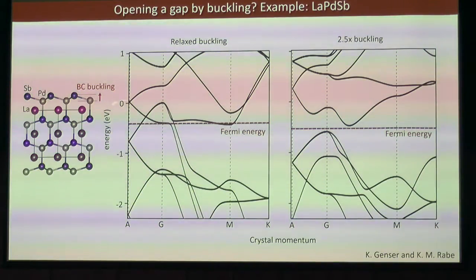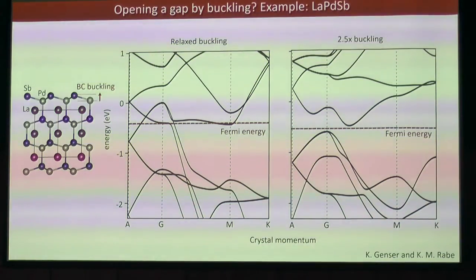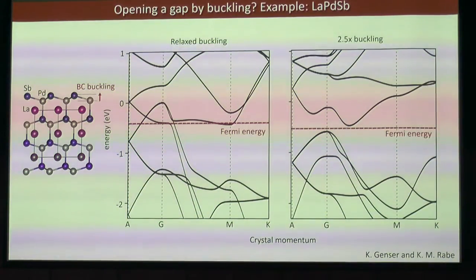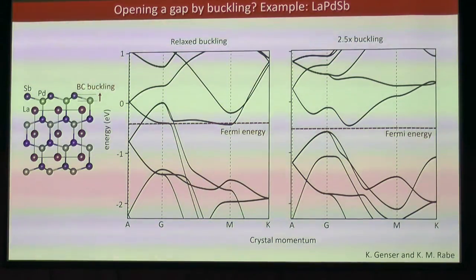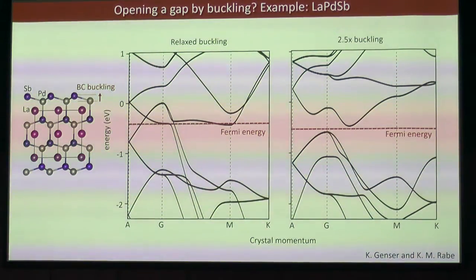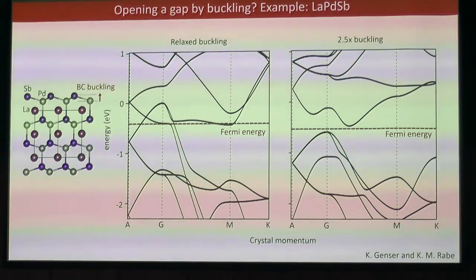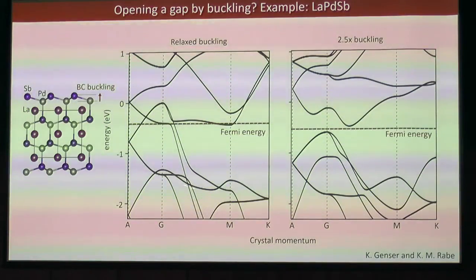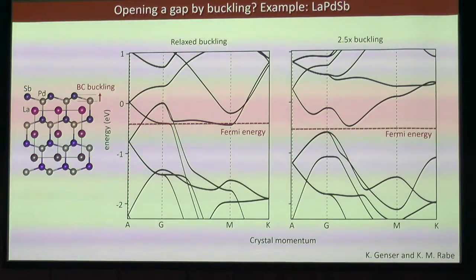Okay. And natively it's a semi-metal with some overlap of about 1 eV. According to Karen's calculations, if you could somehow induce about 2.5 times buckling enhancement in this BC sublattice, you would expect to see gaps opening. So we're trying to see if we can actually do that. Okay, and to start with, we'll start out with just trying to grow these compounds, the natively metallic ones, in the unstrained state.